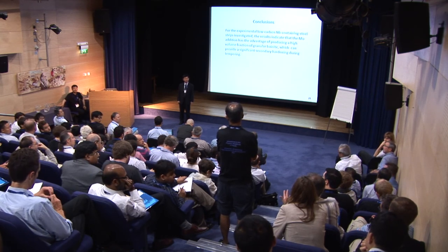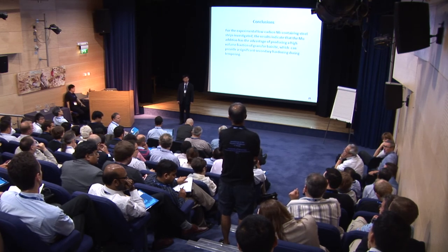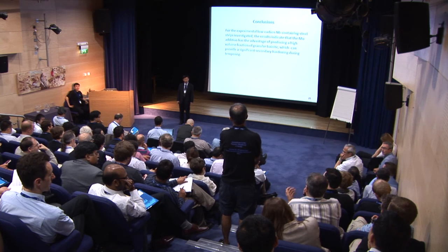Short question. First, thanks for the excellent talk, and it's a very difficult story that you show here, how to characterize the microstructure. I have a question about the EBSD data. You separate between ferrite and bainite here, and you use misorientation profiles. Have you ever tried to use not misorientation profiles but kernel average misorientation or some other type of maps in EBSD, as both structural constituents have different dislocation density, which probably would be better revealed there.